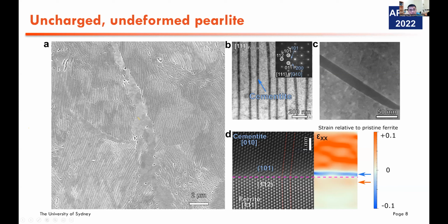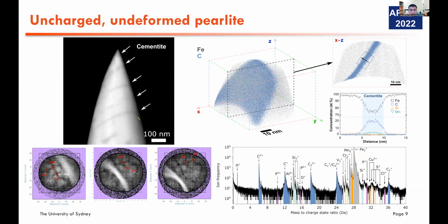I electropolish a tip and then mill it with the FIB technique to finally locate a cementite layer just on top of the tip, and run the standard atom probe tomography experiment with voltage mode. And we observe this 1D concentration profile across the interface. And you'll see that the value is a little bit lower than the expected one.